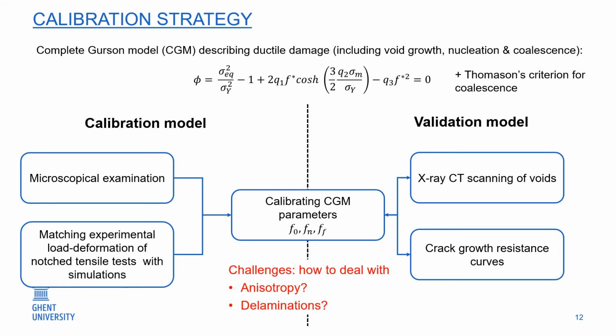Afterwards, the goal is to validate the model by assessing the void evolution using X-ray CT scans and by performing experimental toughness tests, and hereby comparing the crack growth resistance curves with numerical simulations. Two important challenges have already been indicated. How are we going to deal with the observed anisotropy and delaminations?